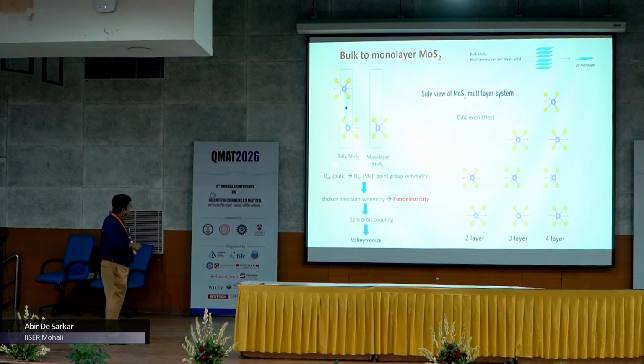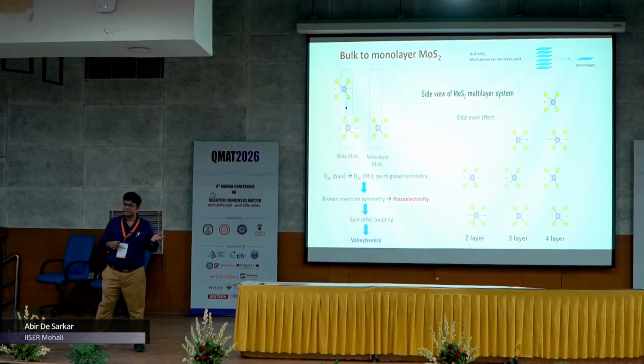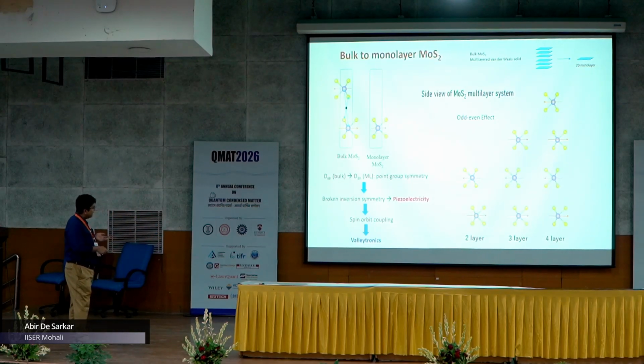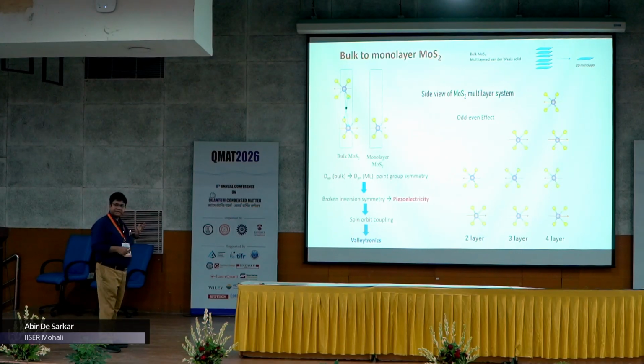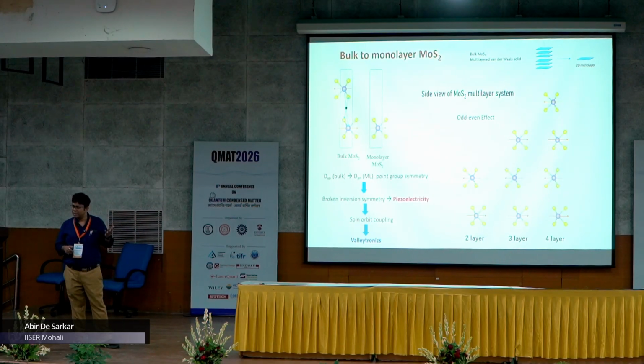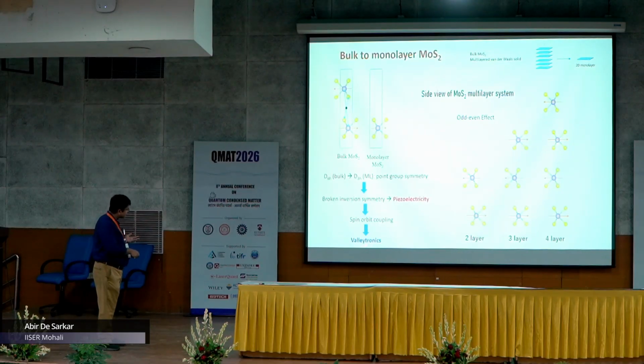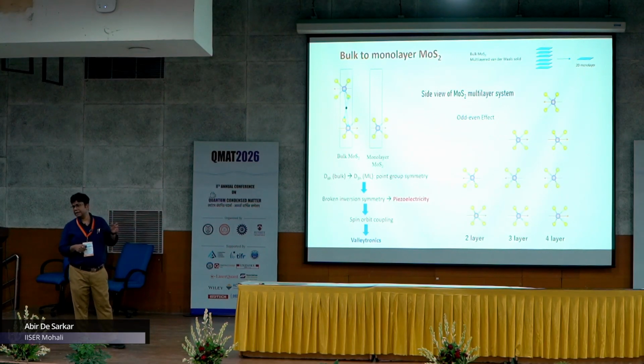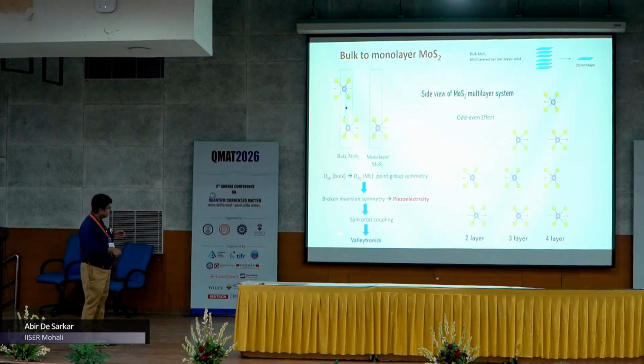When going from bulk MoS2 to single layer MoS2, the point group symmetry changes from D6h to D3h. The symmetry is lowered and the inversion symmetry is broken, for which piezoelectricity arises in single layer MoS2. On top of that, spin orbit coupling simultaneously occurs in single layer MoS2, and that leads to the emergence of valleytronics. This is a property which also emerges in single layer MoS2. I'll talk about this property slightly later in my talk.